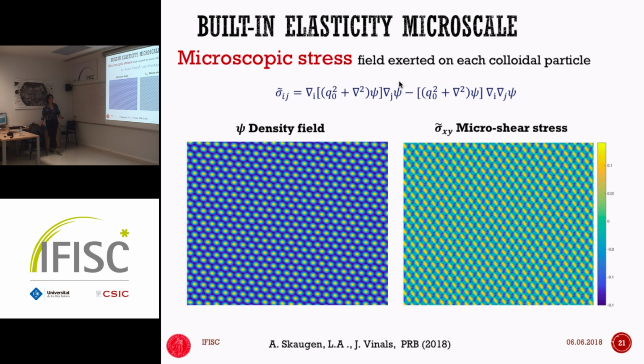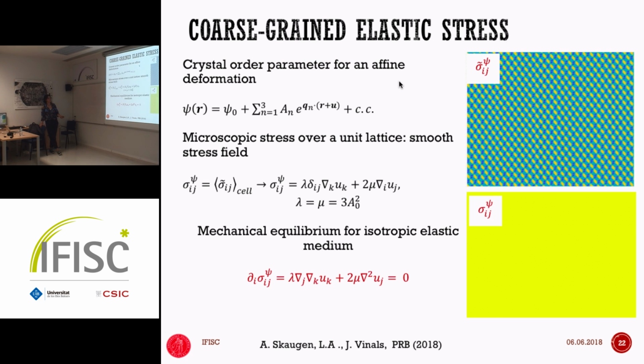So if I plot the stress here, you can see that it acts at the level of these individual atoms, right? And it oscillates at the level of the lattice. However, if I coarse-grain it, if I average it over a lattice unit, I can produce a uniform field that is smooth on scales larger than the unit lattice. So this field can be used to couple the microscale with the macroscale because it's continuous. Okay, so it leads me into the continuous elasticity theory.